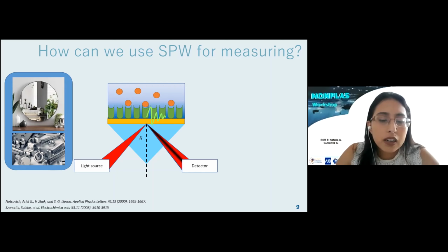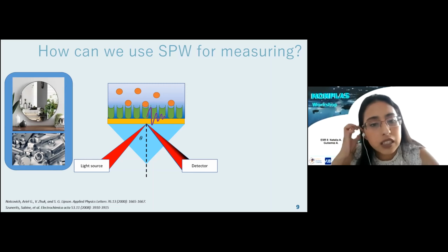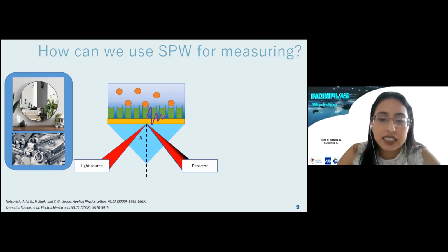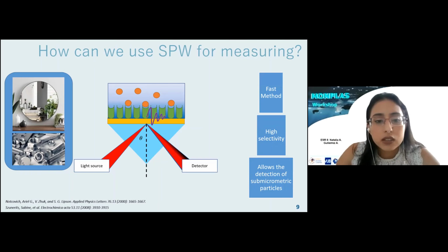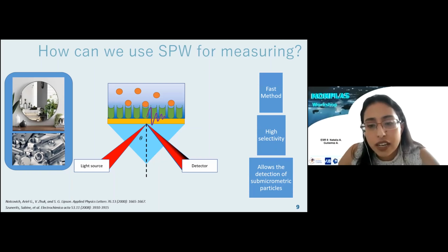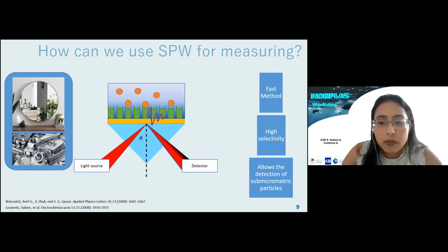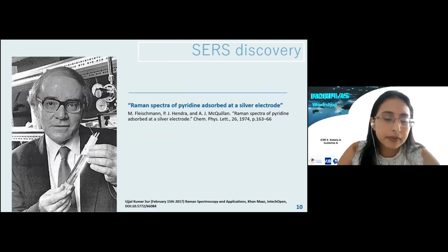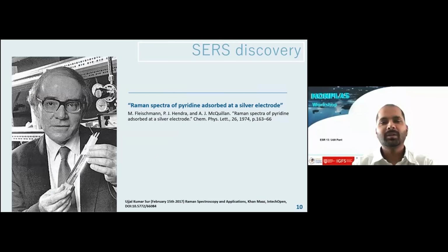Besides this, these techniques also enable us to use a binding layer, which will be able to attach, for example, to our target compound. And when there is this attachment, then there is going to be a change of the index of refraction, which could be detected in the system. So this technique will provide us a fast method of detection, also a very high selectivity, and allows the detection of submicrometric particles.